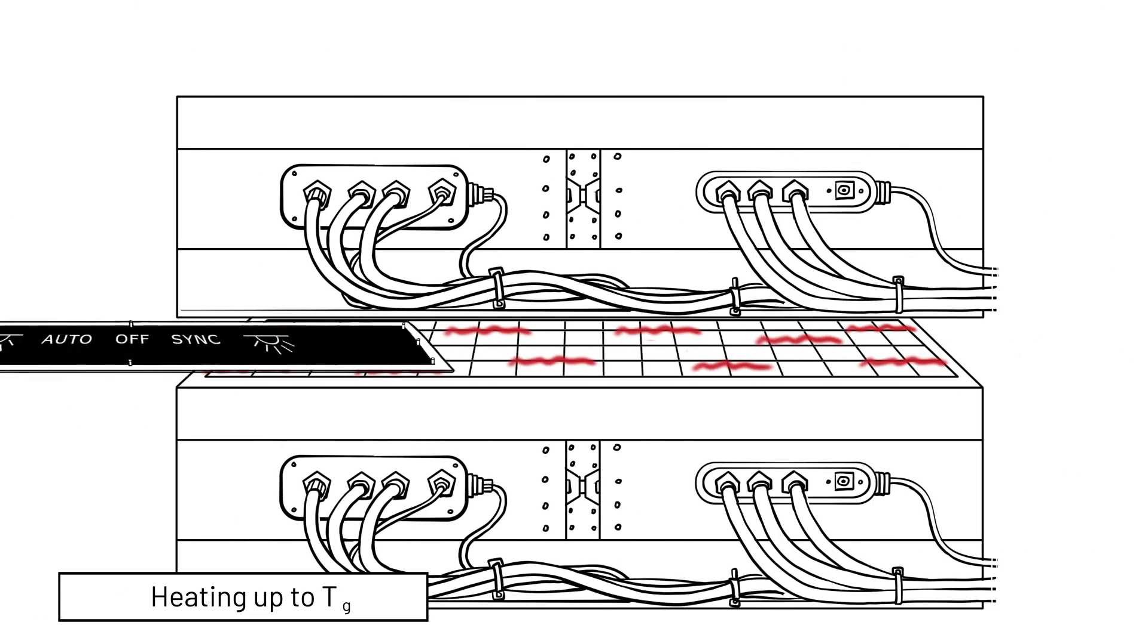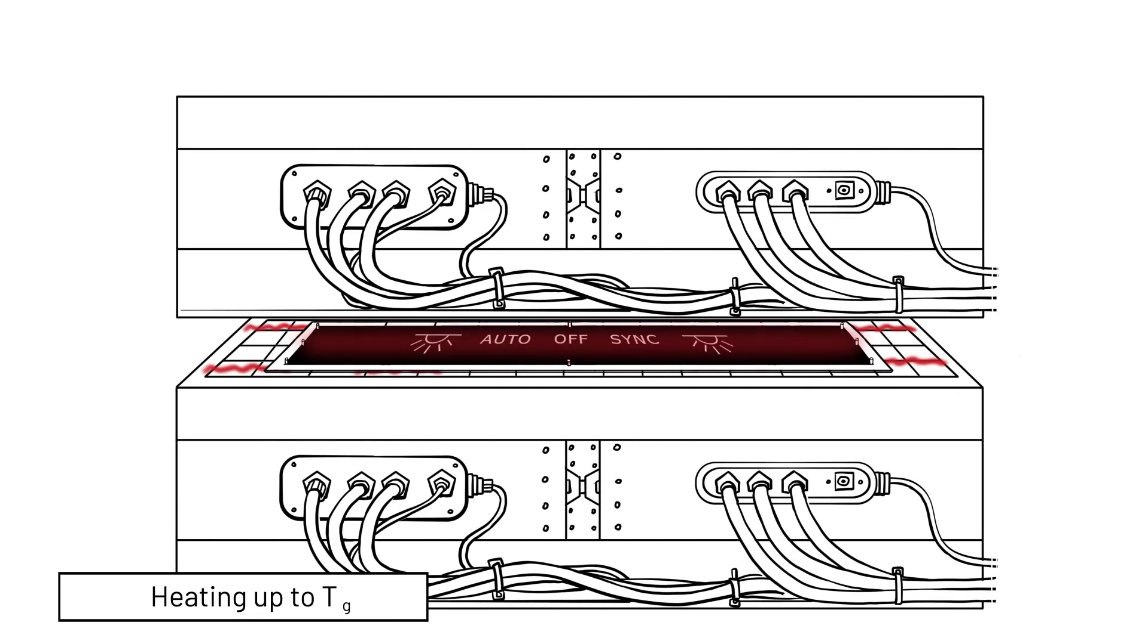Contactless heating of film from both sides just up to glass transition temperature, not melting temperature as in traditional vacuum forming.